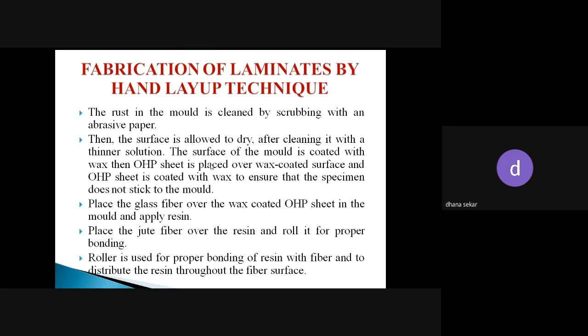First, we prepared a mold, and we cleaned the mold with the help of abrasive paper. After that, we applied wax over the mold. After that, we placed the OHP sheet over the wax. Again, we applied the wax. Then we placed the glass fiber with a size of 300 by 300. After that, we applied epoxy resin, and we rolled it using a roller for equal distribution over the entire surface of the layer.